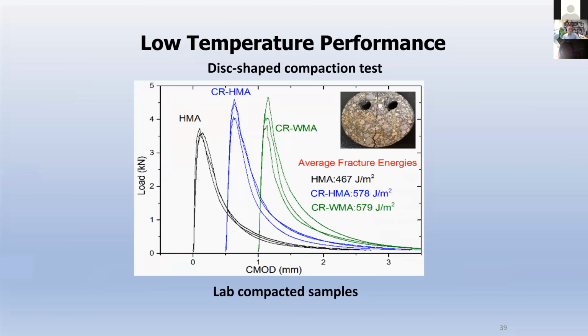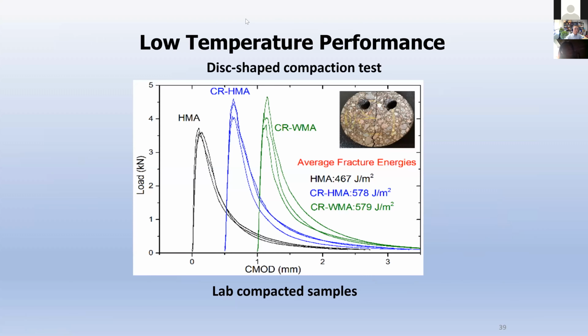And another one I really want to show you is the low temperature performance testing. Of course, you can see here's the load again, and on the x-axis here is CMOD, which is the displacement during this test. Every time you do the test, if the area underneath the curve is small, that means the material is easily cracked, because it requires less fracture energy to crack it.